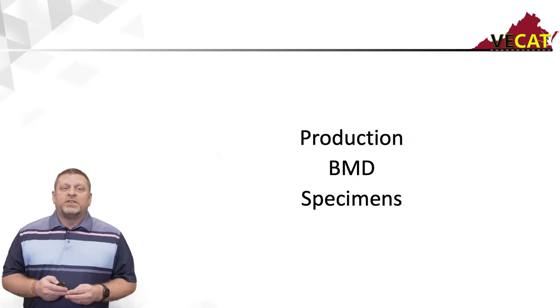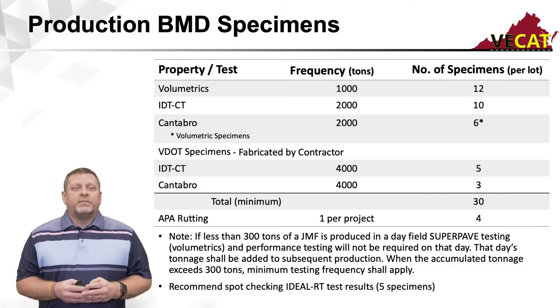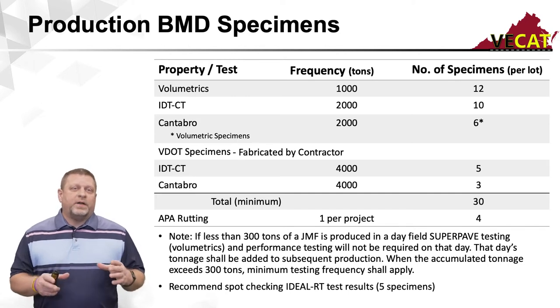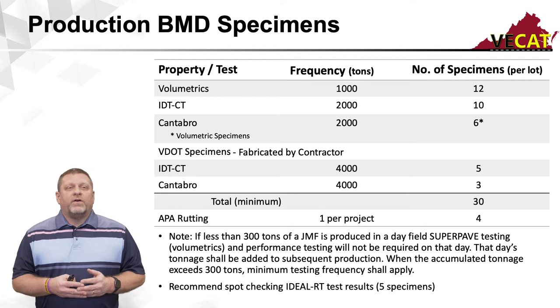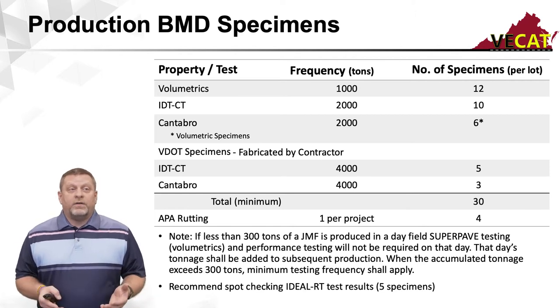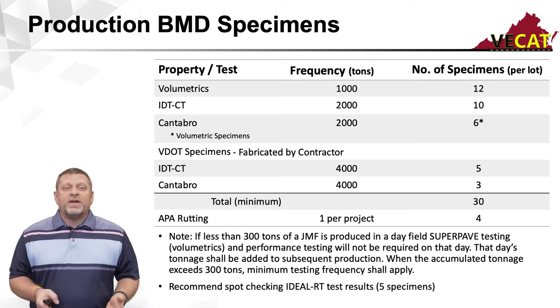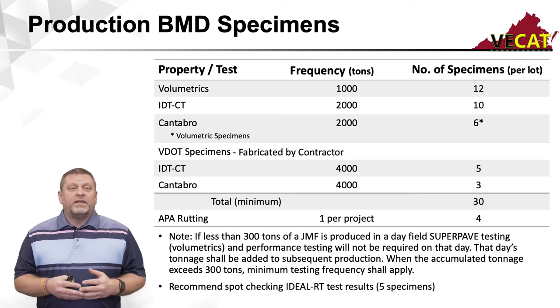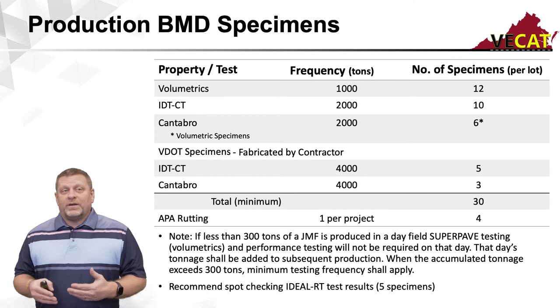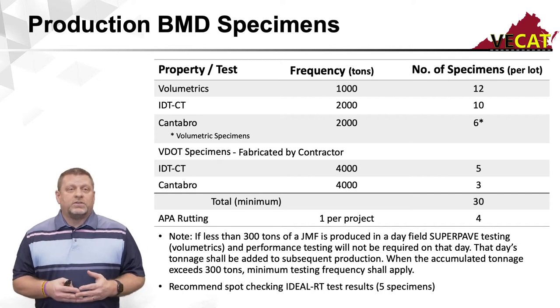Now let's talk about production samples and what we've got to do to make production BMD specimens. This table puts it into comparison per lot. For a 4,000-ton lot — a standard lot in Virginia — we do volumetrics once per 1,000 tons, so a minimum of 12 volumetric pills. The IDT-CT requires a test every 2,000 tons, and since it takes five specimens to get one CT index value, you need a minimum of 10 specimens. I would recommend making seven per test instead of five, in case voids are out of range.